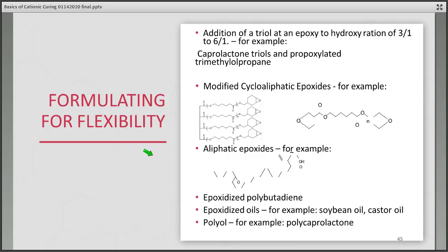For flexibility, there are various methods you can use. You can add a triol, with an epoxy to hydroxy ratio of 3:1 to 6:1, such as caprolactone triols or propoxylated trimethylolpropane. You can use modified cycloaliphatic epoxides, which have these long aliphatic chains here, and then what's going to be here, will give you that flexibility once they cure in your system. Or just straight aliphatic epoxides work well. Or you can use epoxidized polybutadienes, epoxidized oils like soybean oil or castor oil, or polycaprolactone for flexibility. So there are numerous ways you could formulate to make a system more flexible than, say, your baseline formulation.